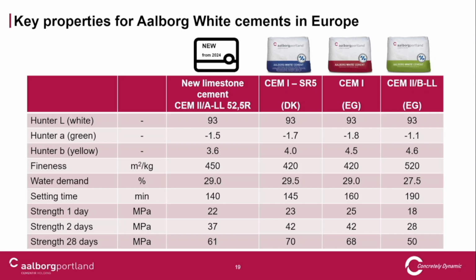If you compare to the cement from Aalborg today and the two Egypt cements, 1-day strength is 22 megapascal, 23, 25. So we will have more or less the same 1-day strength as the CEM I cements, and the fineness will not be much higher. We also see that the setting time should be a little reduced because of the nucleation effect.